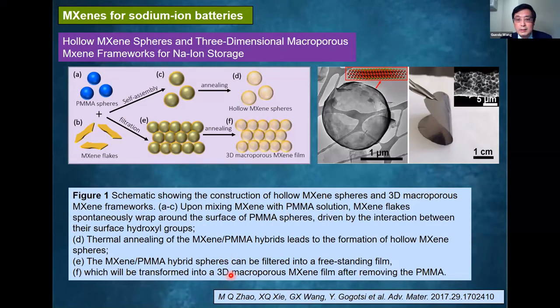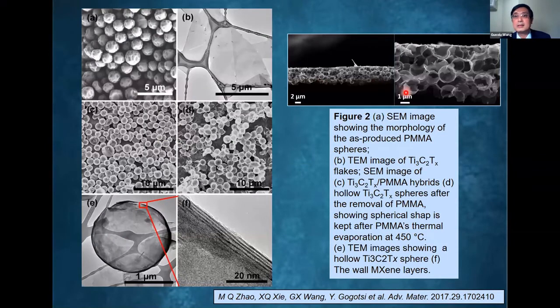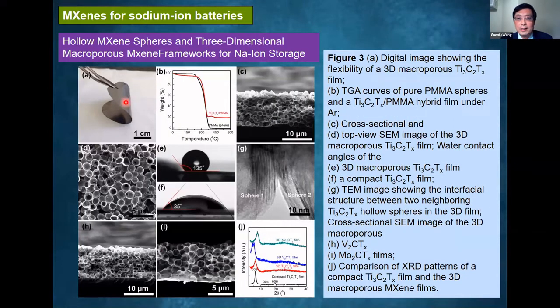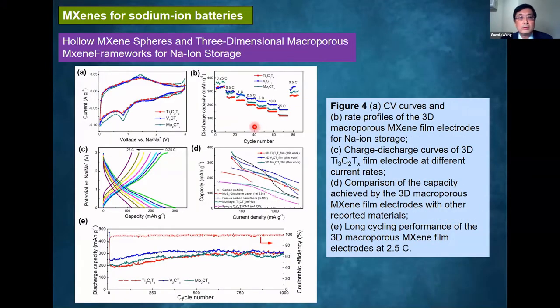And then later, Xiuqiang Xie collaborated with Meng Qian Zhao in Drexel University. They developed a method to use a hard template because individual MXene nanosheets are quite flexible. We can make hollow MXene spheres. So this is the SEM cross-section image. You can see when you make a paper-like thin film, the cross-section is composed of individual hollow MXene spheres. And this paper is flexible. And when we directly use hollow MXene spheres as electrodes for sodium-ion batteries, you can see we can further extend the cycling stability to more than 1,000 cycles.